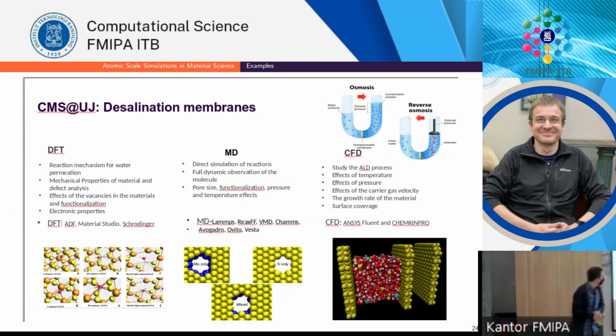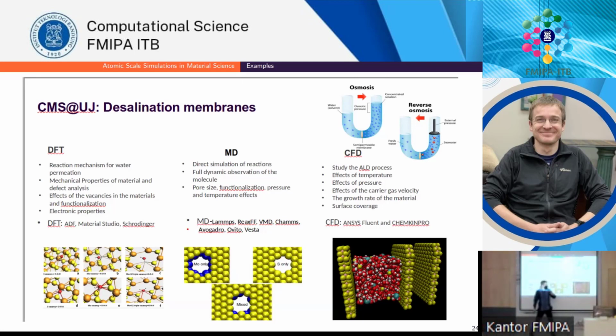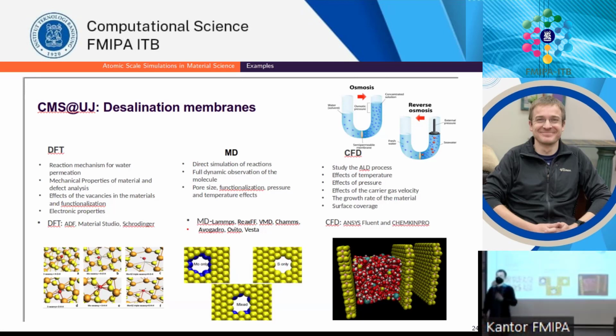All right. So the main part of that project was actually looking at this setup of molybdenum disulfide sheets in the membrane and the water with ions trapped inside. This sheet has a hole in the center of this shape. Basically, the main point of the study was to change the diameter of that hole from 1 to 5 angstrom, roughly, to see the effect on the diffusion of the water and the ions through it.